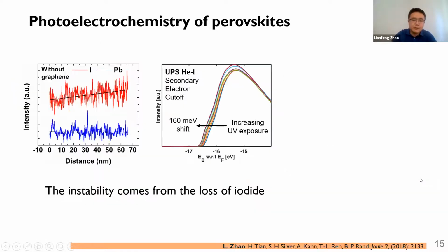So we further studied the mechanism that induced the n-type doping of perovskite, and we found that it is related to iodide loss in perovskite. As you can see here, on the surface of the perovskite, the concentration of iodide is lower than in the bulk. We further confirmed the iodide loss related to n-type doping based on a polycrystalline thin film. And indeed, from the UPS measurement, we confirmed the n-type doping effect induced by the light illumination. So this means that the perovskites are not stable under light, which is really an instability issue.